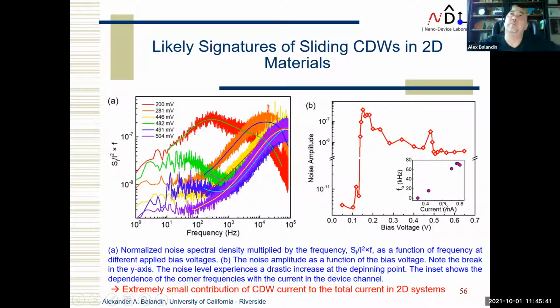So now we believe that we did discover movement of charge density wave in a two-dimensional material. However, it's very different from what people had in quasi-1D materials, because here you have these islands, and the contribution of the charge density wave motion to current is still very small compared to the current through the incommensurate phase. It's like a river with islands. The contribution from the incommensurate phase, which conducts, is much higher. That's why in IVs we don't see this abrupt increase in current, and it also takes much higher fields to start this motion. So the bottom line: you can probably come up with some functionality, but the physics still requires explanation, and could be very different from what we have in traditional charge density wave materials with quasi-1D crystal structure.